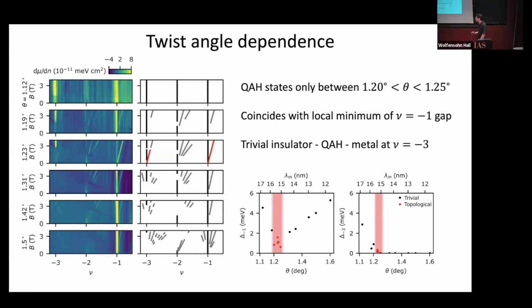A comment that I think is true and isn't really talked about a ton is, people talk about quote unquote Chern insulators at moderate or high magnetic fields, and in some cases relate them back to the topology of the bands at zero magnetic field. I think when you start to apply a magnetic field, it becomes very, very difficult to know, is the topology that you have coming from the underlying bands, or are you just seeing topology of the Hofstadter subbands that are there? So I'm taking the cautious approach, I guess I would say, of assuming that this may be Hofstadter physics rather than related to topology of the bands. But I don't have a good experimental way of distinguishing those two cases, or actually I'm not even sure they're even theoretically particularly distinct. Yeah, thanks.